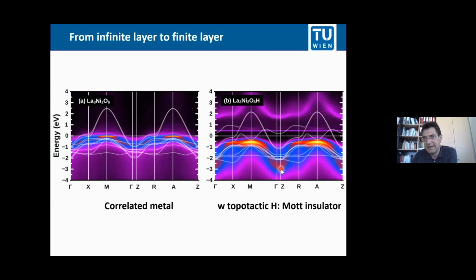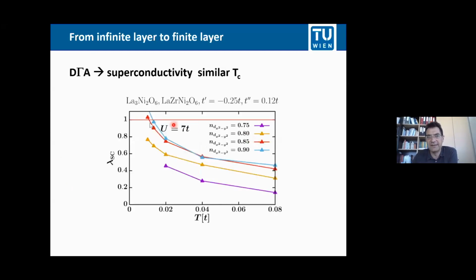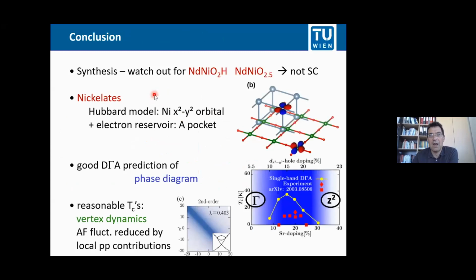Topotactic hydrogen makes your electronic structure very, very different. It's also a Mott insulator. And if you calculate the Tc, you get very similar critical temperatures as for the infinite-layer structure. So these already have started to be synthesized experimentally, but doped systems with superconductivity still have to be found.